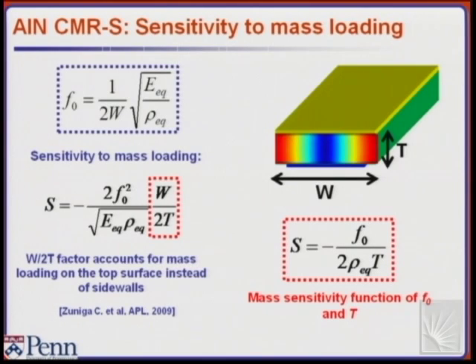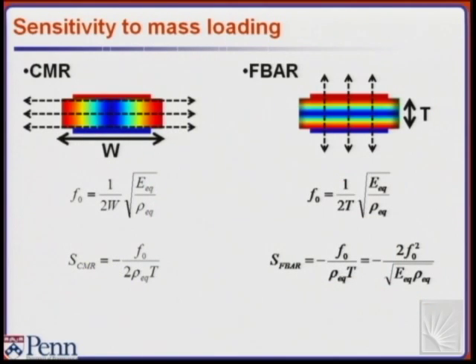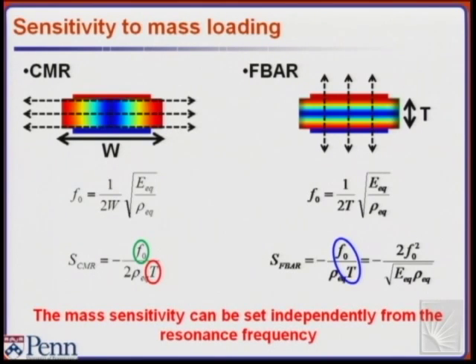When you make a sensor, sensitivity is not the only variable in the game, right? It's actually the limit of detection that matters. But let me first compare sensitivity to mass loading of a contour-mode resonator to an F-bar, which I think is our closest competition. F-bar or quartz crystal: basically a device that vibrates across the thickness. They use the thickness to set the frequency. If you look at our sensitivity, I've already told you that frequency and thickness are the two key parameters. For an F-bar, it's just frequency, because frequency and thickness are related. So when you scale the thickness, you're also scaling the frequency. Instead, for our devices, you can independently set the sensitivity from the frequency, right?